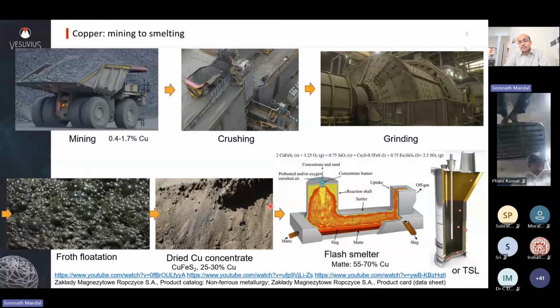This copper concentrate powder is then charged into a flash furnace, as you see here, along with some amount of quartz silica as a flux. What exactly happens here is that your iron sulfide gets oxidized, about three-quarters of it, and forms FeO. That FeO then reacts with the silica to form iron silicate, or fayalitic slag. So now you have a matte, which is the product from this, containing 55 to 70% copper.